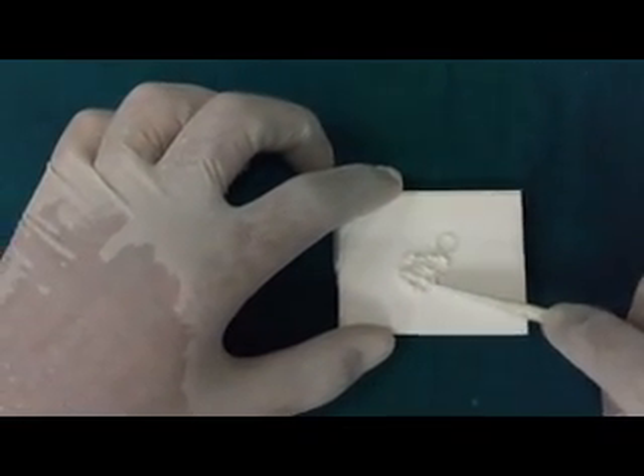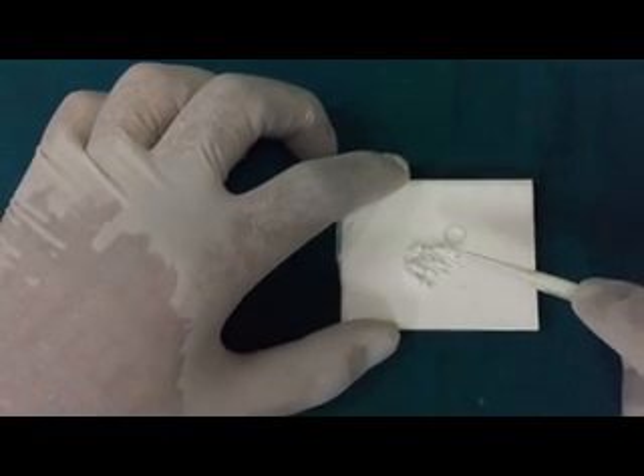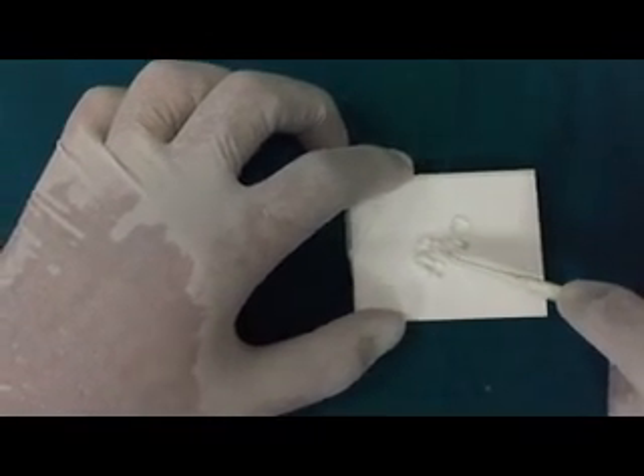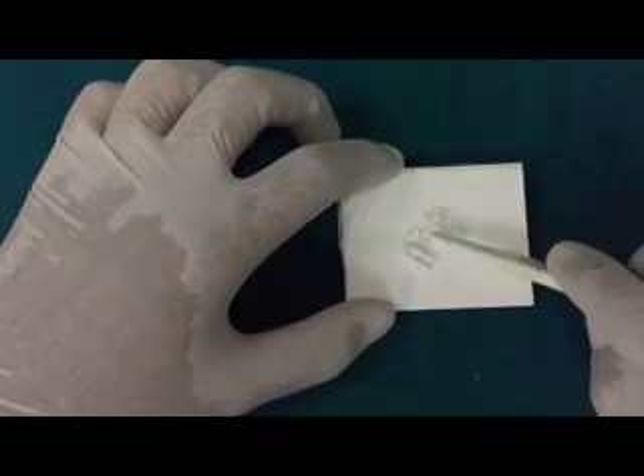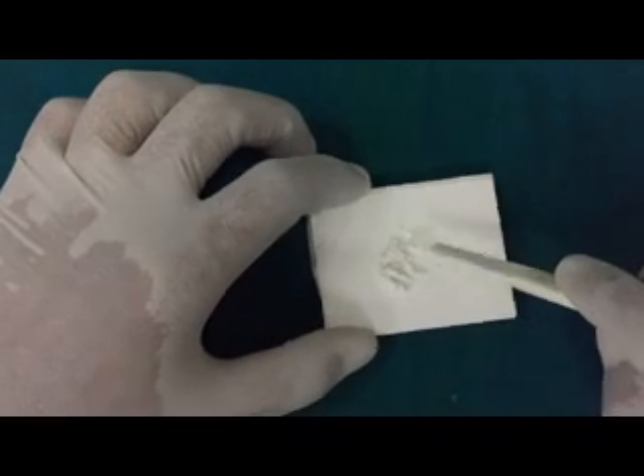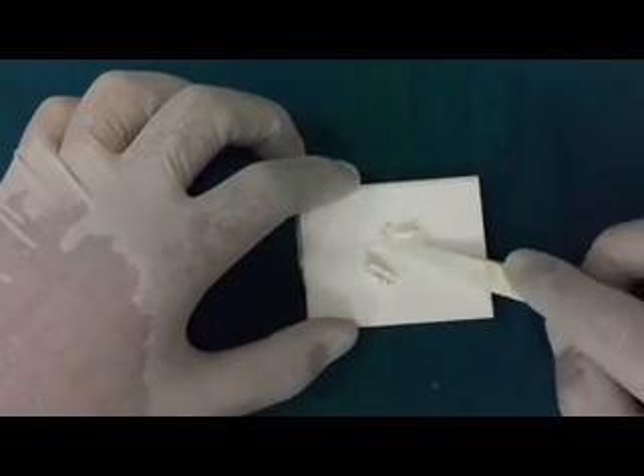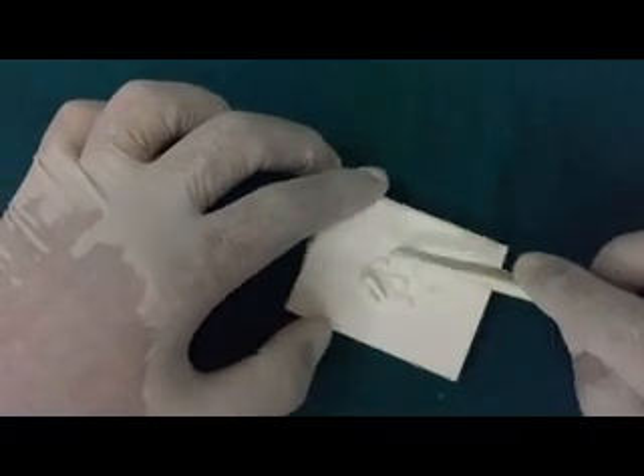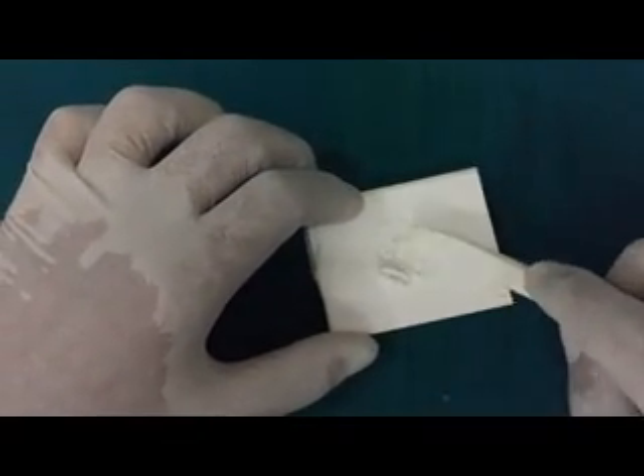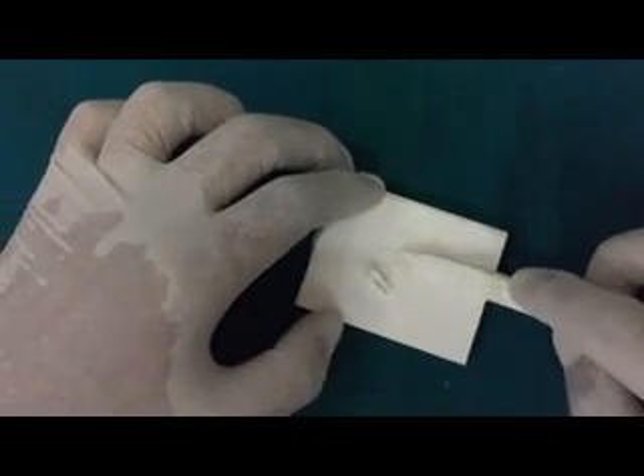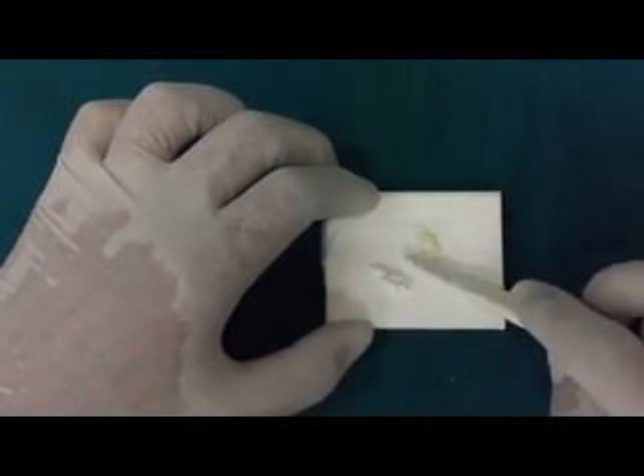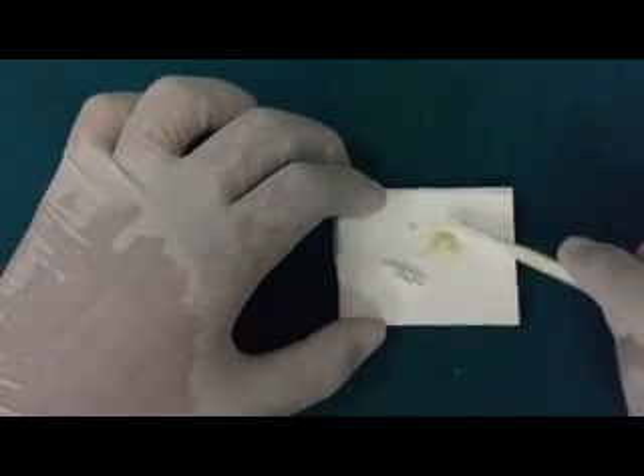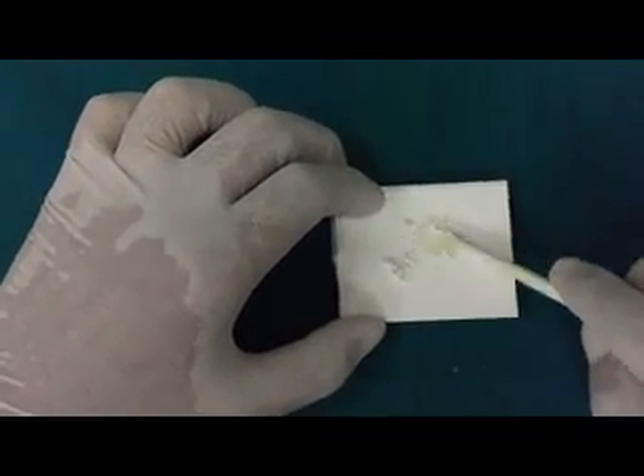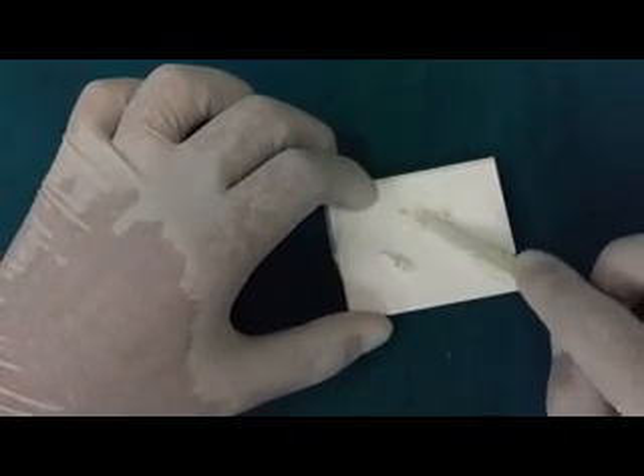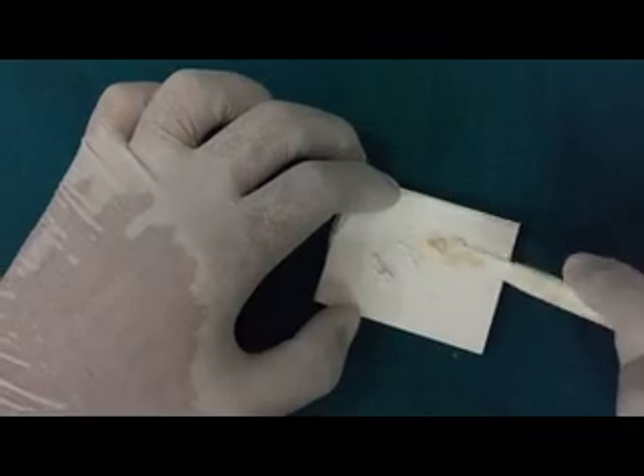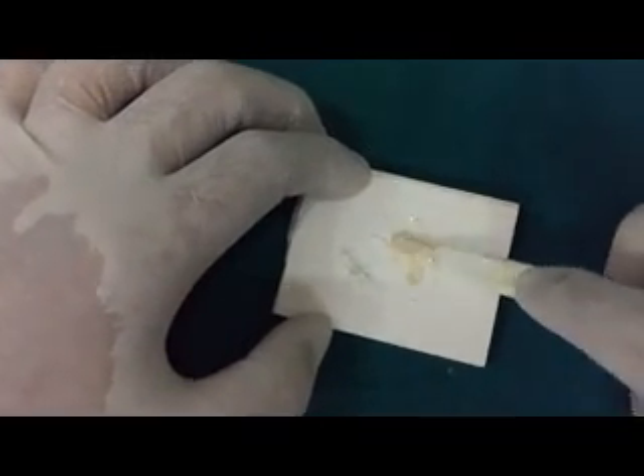We do not introduce the cement powder into the liquid in parts like we do in zinc phosphate cement. On the contrary, we introduce the powder into the liquid in bulk. And the purpose of the mixing is only to wet all the particles with the liquid and not actually to spatulate the material. The purpose is only to wet the powder so that each particle of the powder is coated by the liquid. As we mix the powder into the liquid, we can see that there is a glossy surface which is maintained on the mixed powder.